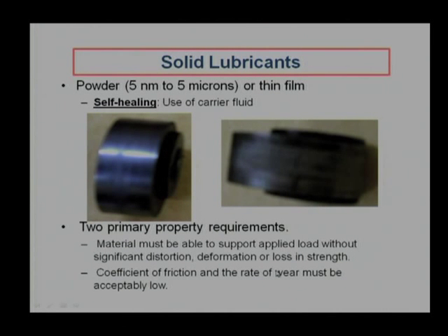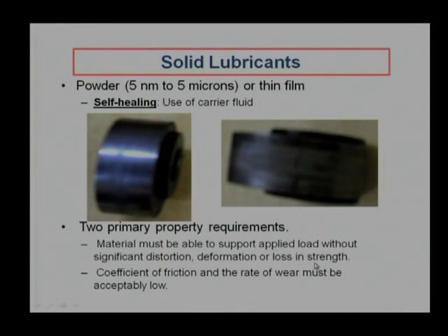Deformation or loss in strength should not occur, and they should not show creep behavior. Most polymers have creep behavior. If you apply a stress of maybe 20 or 25 megapascal, they will show good performance initially, and with time the performance deteriorates. Because of creep, they start flowing and show different properties. So, as far as possible, they should not lose strength. If solid lubricants lose strength, we should not use them for that kind of load. We should use them at a slightly lower load, which can be carried without creep behavior.